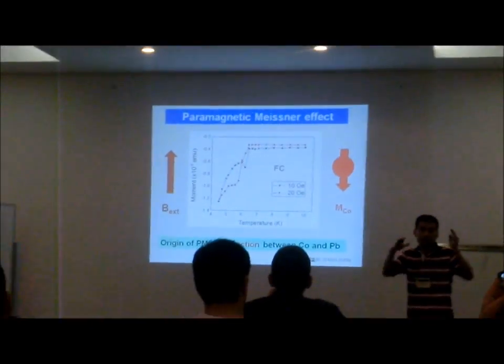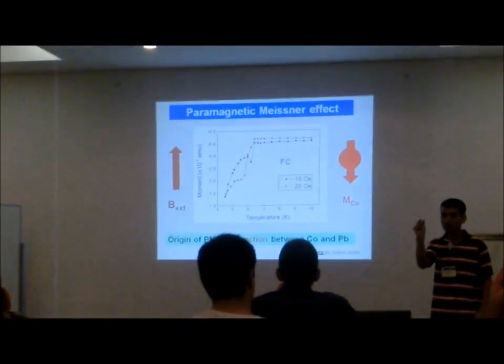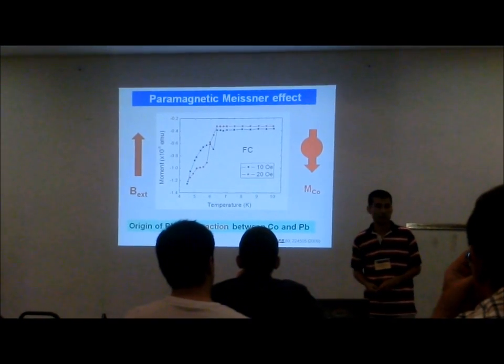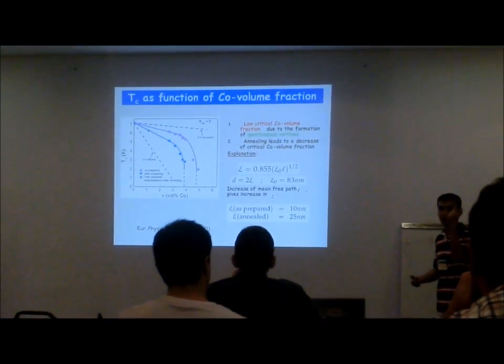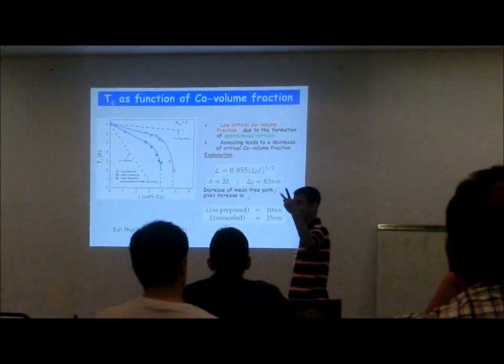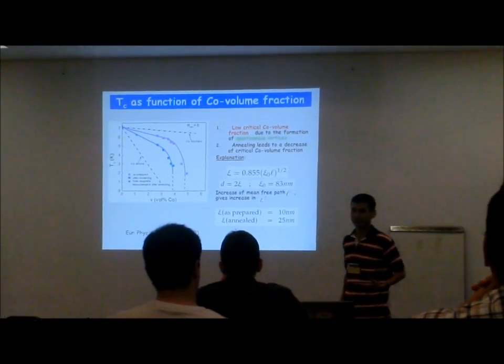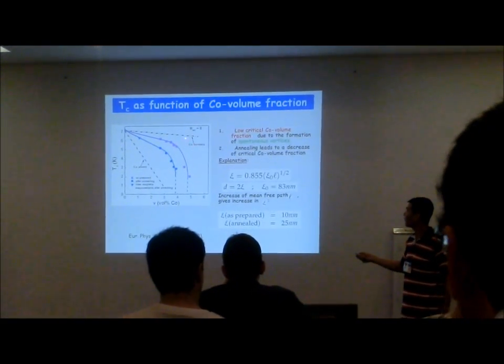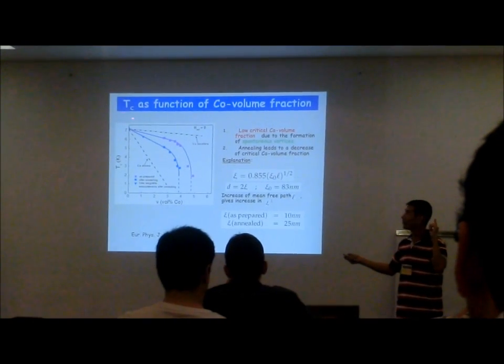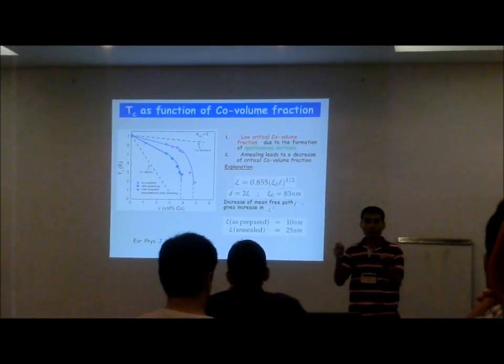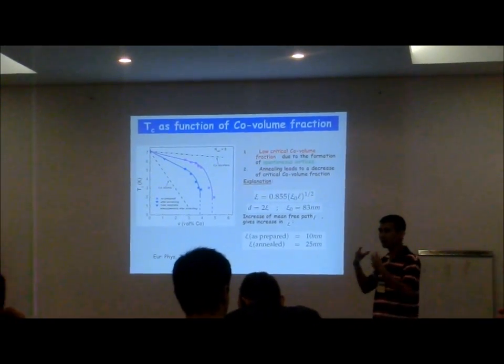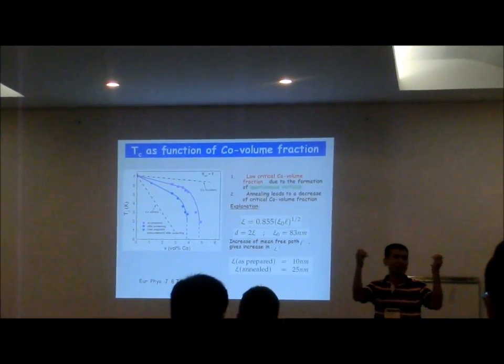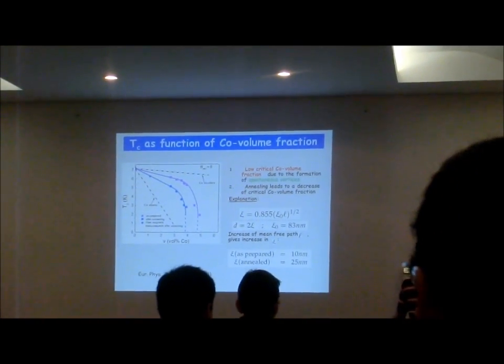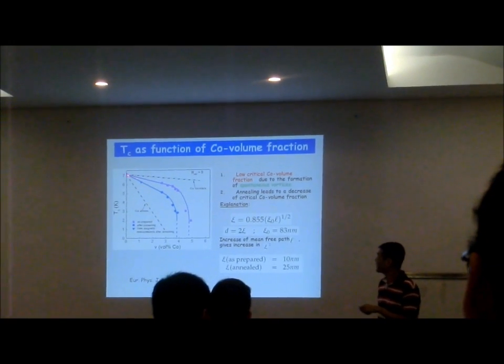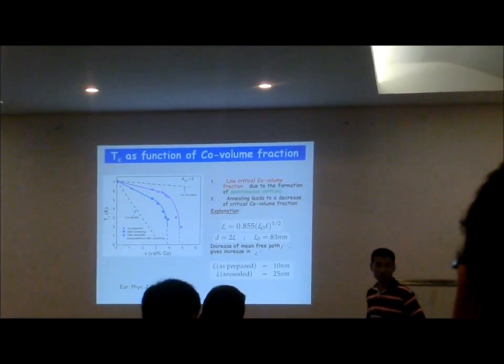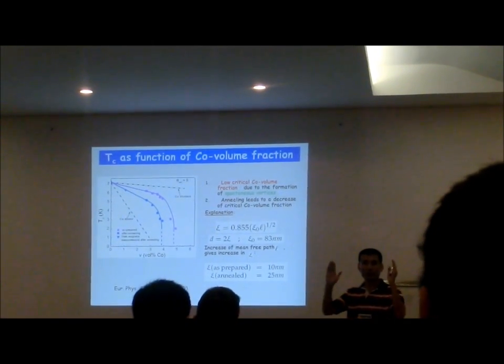With cobalt particles it will change for sure. But when the magnetic field is very small, it only depends on the orientation of cobalt particles. Of course, we still have the proximity effect and the formation of spontaneous vortices. So the density will decrease. So if we compare our sample with the only proximity effect, so here this line is copper nanoparticles inside the lead. So we have cobalt and they have copper, and the diamonds they are almost exactly the same. This comes from a graduate. And then you see, even you can reach 70% of copper volume fraction. Volume fraction of copper can reach 70%.